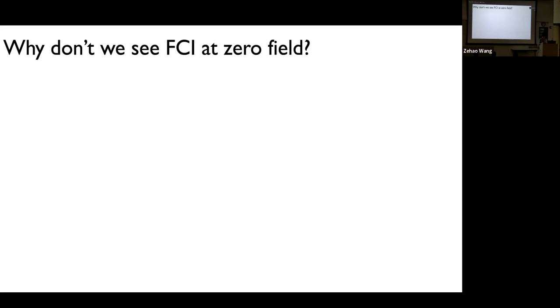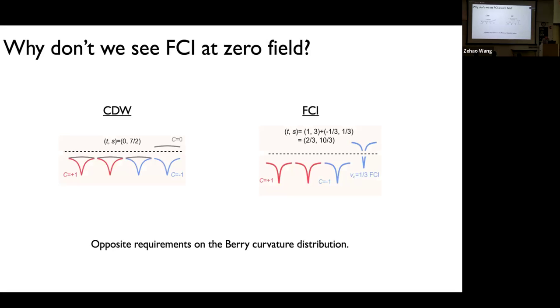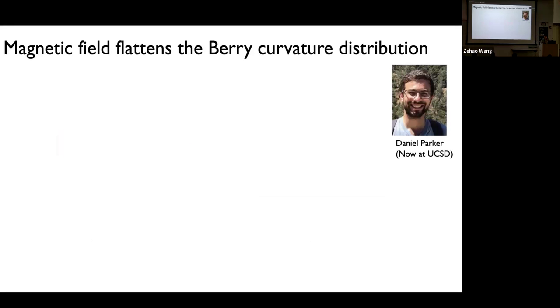So I already alluded to this, why don't we see FCI at zero magnetic field? And the reason is because this Berry curvature distribution is not homogeneous. If you think about, say, the Landau level, because the energy level is extremely flat, then no matter how they distribute in the momentum space, it doesn't really matter because it's homogeneous. However, in this case, it's not quite that, and that's the reason why at low magnetic field we see charge density wave, either trivial or topological, and we need magnetic field basically to help flatten this distribution so that the system behaves more like a Landau level. And you can confirm this with calculation.